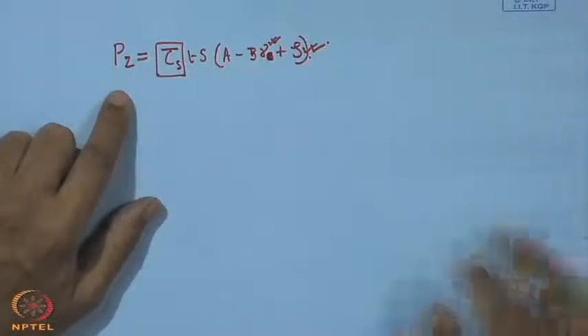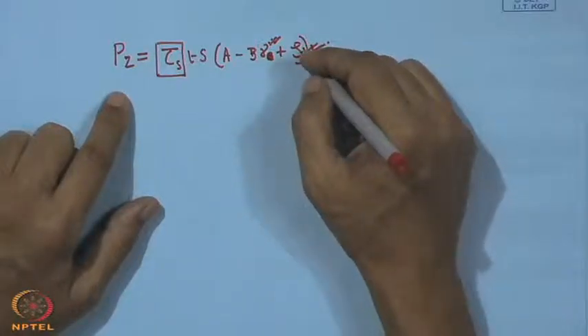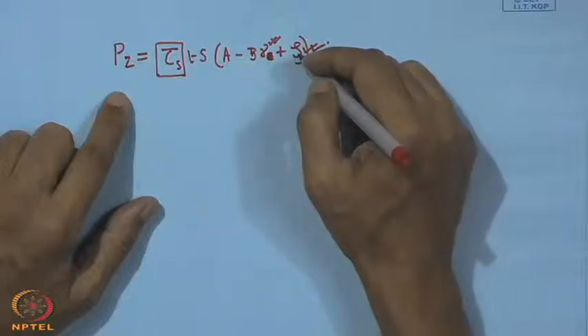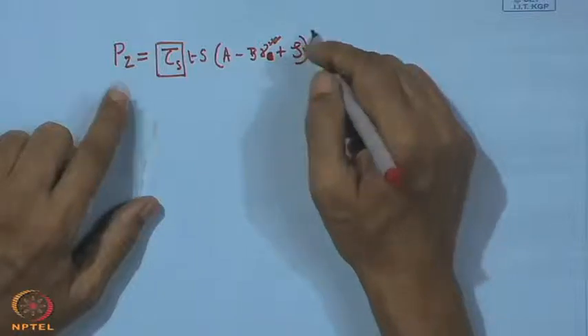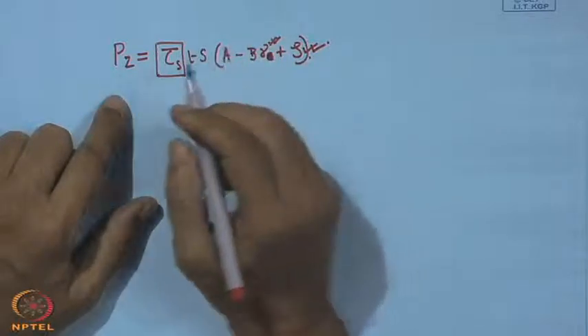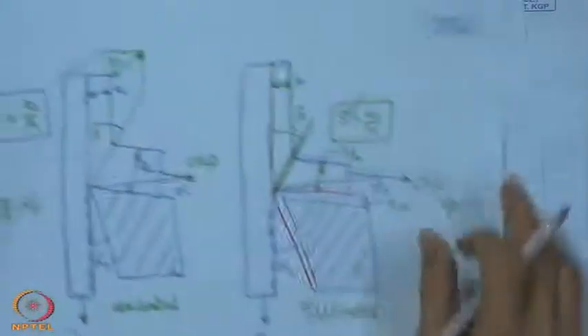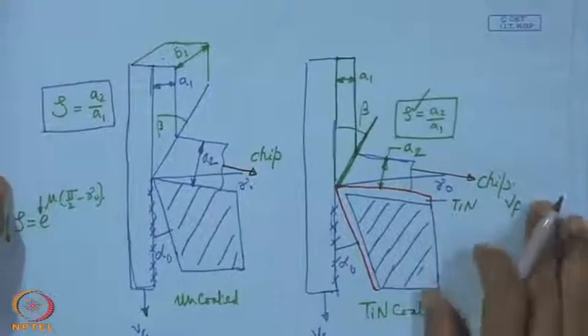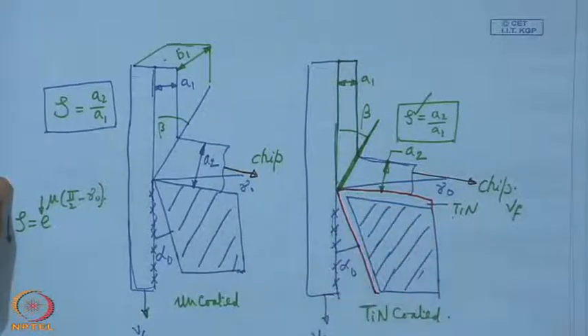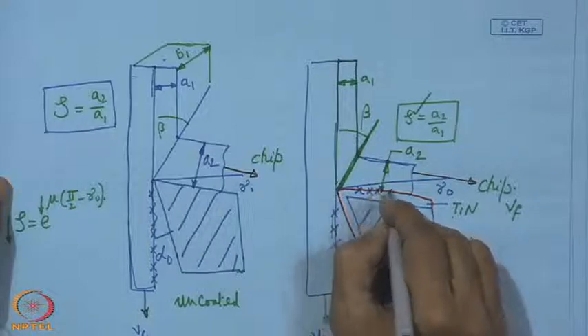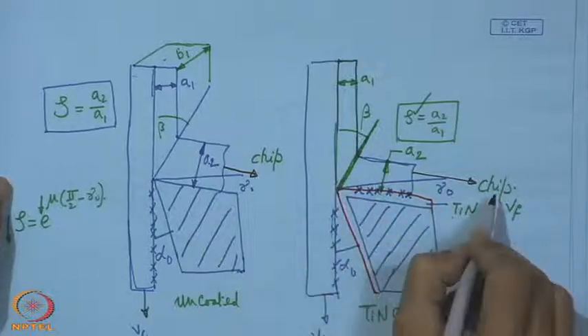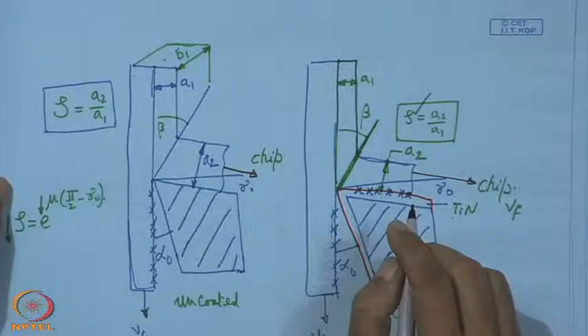Now, what we mean to say here is that titanium nitride is playing a role indirectly, because the value of zeta will be influenced by this titanium nitride if it offers a low friction. So, definitely the value of P z will be brought down, and also, looking at this diagram that we have shown just now, in this zone, if we lower the friction, then the friction force, that means the drag force necessary for moving the chip in this direction, will also be reduced in comparison to what we expect here. It is because of the coating.